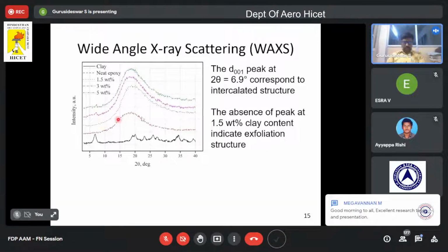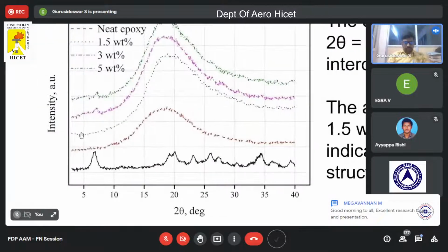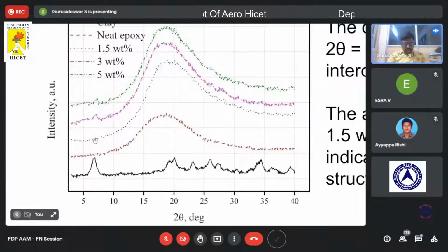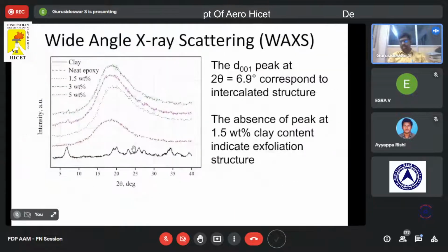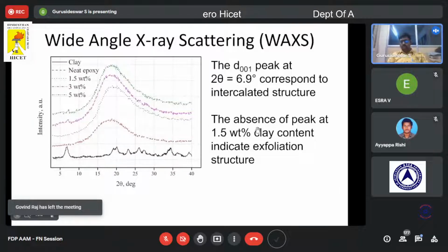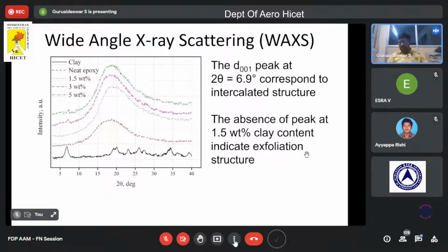If you observe carefully, maybe I can zoom it. If you observe carefully, we do not see any peak for 1.5% clay. That means 1.5% clay provides good dispersion. So this is what we understand from this wide-angle X-ray scattering. The absence of a peak at 1.5% clay content indicates exfoliated structure. As I told earlier, the exfoliation indicates random dispersion of clay in epoxy. Okay, so this is what we understood from the wide-angle X-ray scattering.